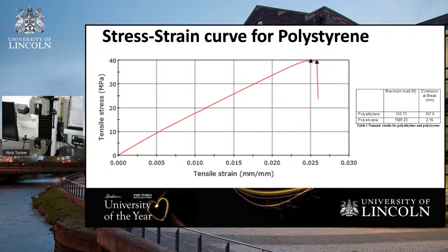But if I take a very small quantity of acetone and put it on our sample, we now magically find that if I try that bending experiment, it snaps really easily. And you can perhaps see that there's been solvent damage on the surface. The acetone has begun to dissolve the polystyrene, allowing the formation of micro cracks, which means that our properties suddenly become rubbish.